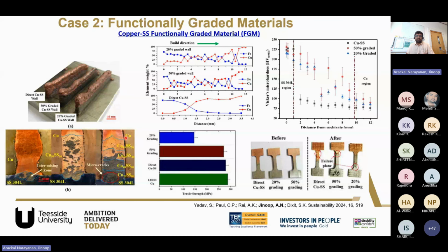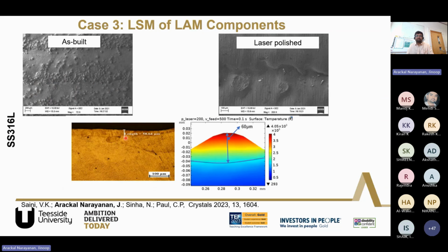Also, we did similar studies on copper stainless steel wall structures. The copper stainless steel direct joint was made, which was defect free. But when we went to the 20% graded structures, we could see that a lot of defects were observed in the samples, micro cracks were observed, and we could see that the mechanical properties reduced significantly because of the higher thermal stresses or thermal cycling that is happening during the process.